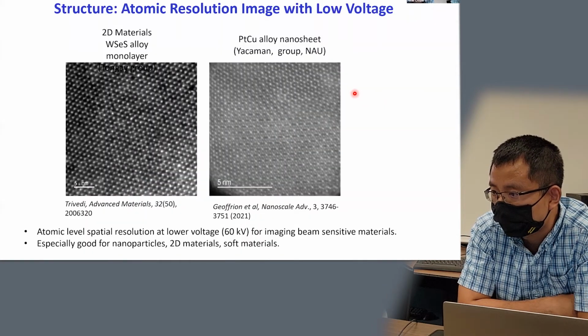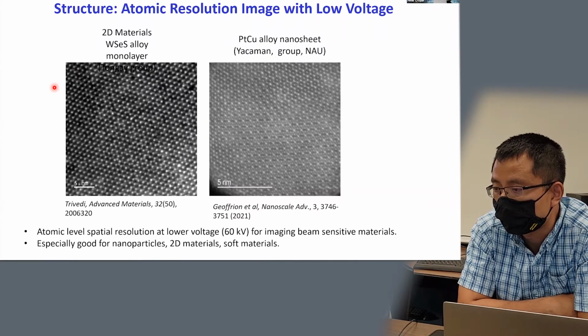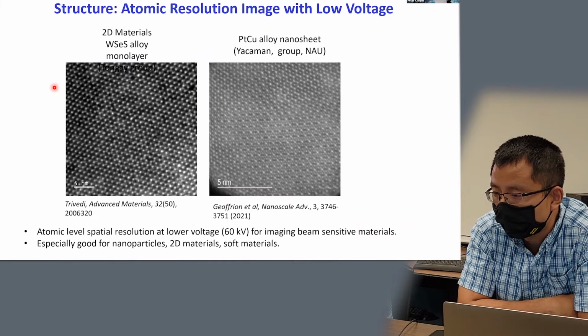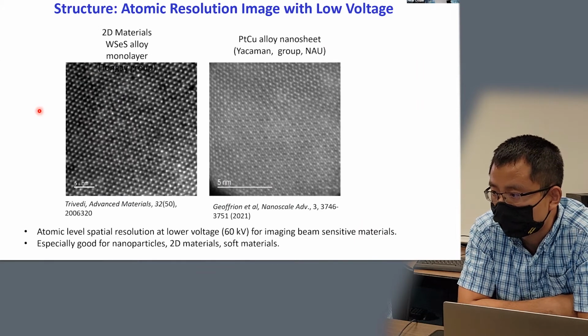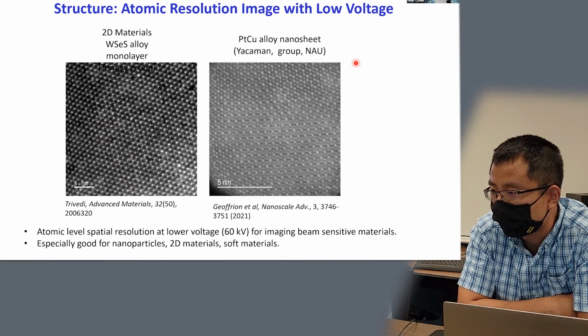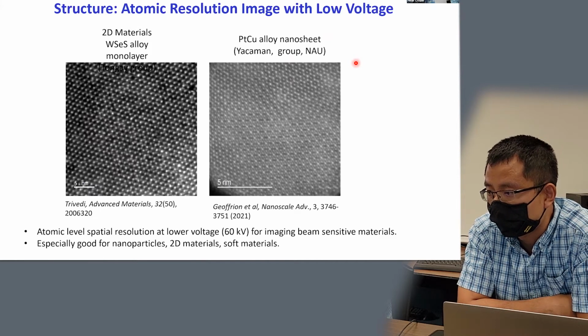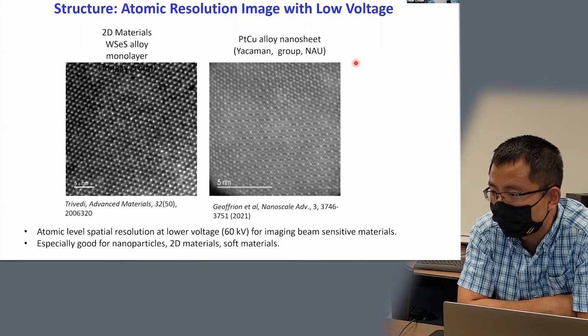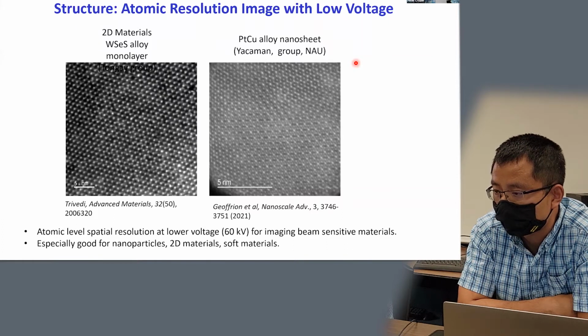Here are some examples where we use the low electron beam voltage to image atomic structure. The material on the left is a 2D monolayer, a tungsten, selenium, sulfur Janus monolayer from the Photonic group at ASU. And the right image shows a platinum and copper alloy nanosheet, which is sampled from the Northern Arizona University Yacaman group. So these images show that the microscope offers really good spatial resolution.